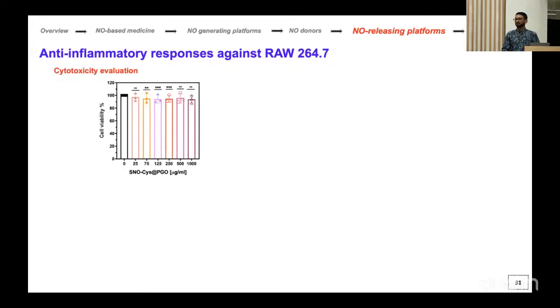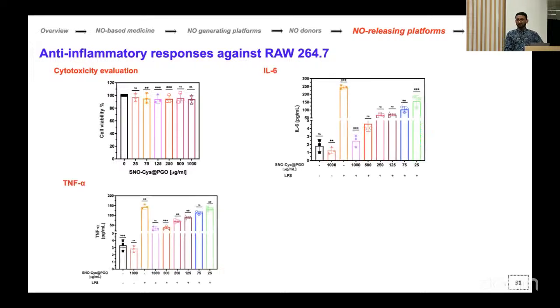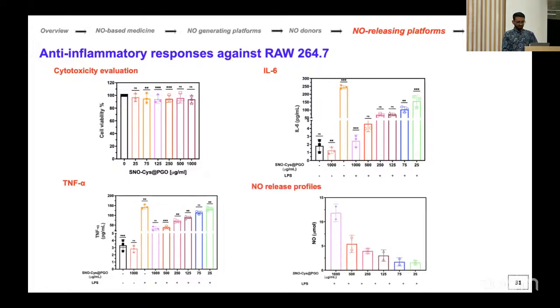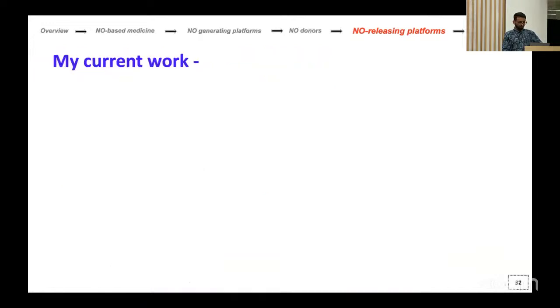Anyways, then we looked at the anti-inflammatory effects against RAW macrophages. We show that our formulation under different concentrations is very much viable with the macrophages. And then we stimulate them. The first one was the M0 stage, when you don't stimulate these cells, and then the M1 stage when you stimulate them with LPS, and we look at the effects. And then we show using the Griess assay that this effect is confirmed by the production of nitric oxide.